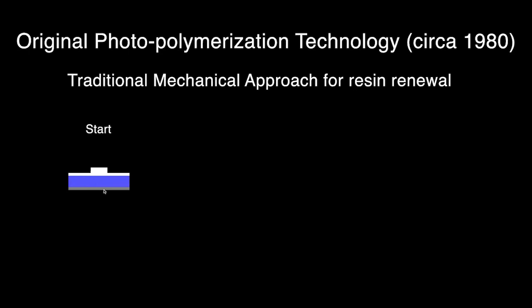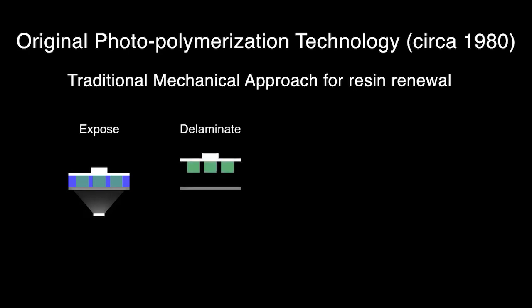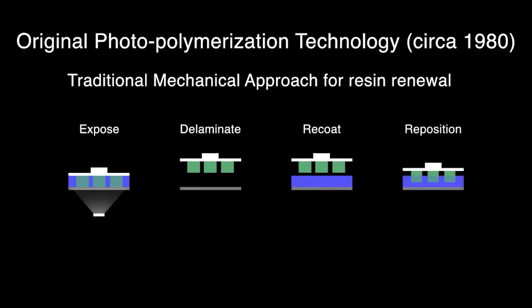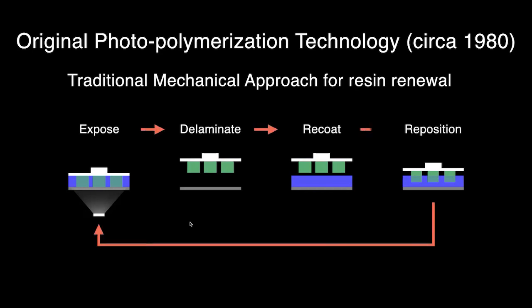You basically sandwich a thin layer of liquid between a platform and a window. You irradiate a two-dimensional pattern, cure that liquid, and now you've cured and made a pattern, almost like lithography, like positive lithography. And then you have to make the next layer. And so somehow you have to delaminate that from the surface. You have to bring in more liquid. You have to reposition the part and do it again, and repeat this over and over again.